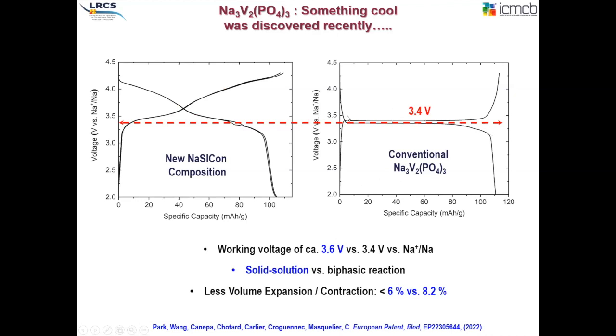Besides the intermediate phases that I demonstrated earlier, here we have a full solid solution from the beginning to the end, with two waves, okay, but a solid solution occurring. And interestingly as well, this new material, new composition, leads to a smaller expansion and contraction upon electrochemical cycling. So this is pretty interesting in terms of applications.